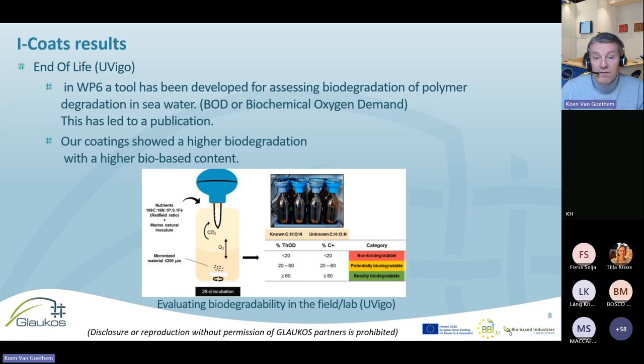Now those two, as well the fibers as the end products, the nets or ropes, were tested on end of life by the University of Vigo, a partner of Glaukos project, and tested on BOD, the biochemical oxygen demand. And this has led for them already to a publication, which is public. Our coatings, they showed a higher biodegradation if we increased the biocontent. If you remember the slides which we provided you with on a definition, there is actually a link. If you increase your bio-based content in your coatings or overlay finishes, the product would biodegrade quicker.